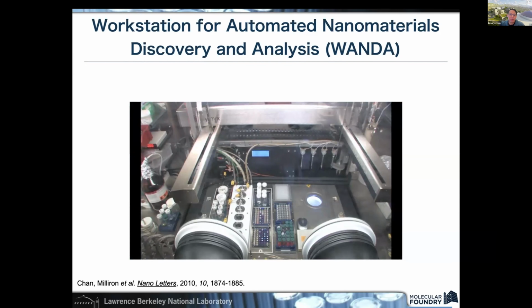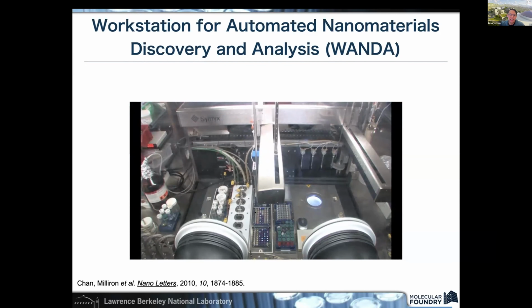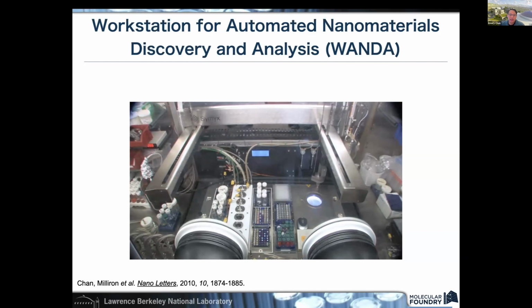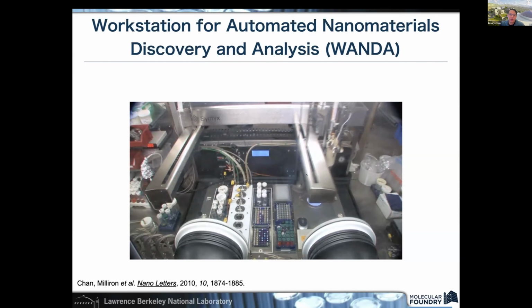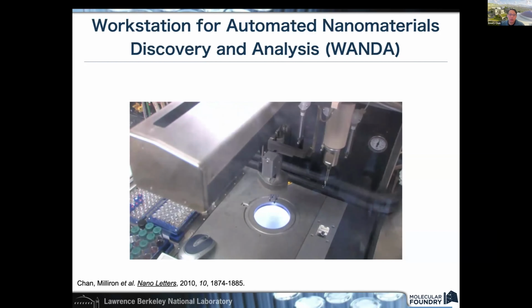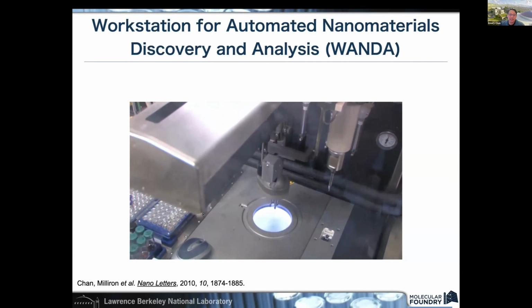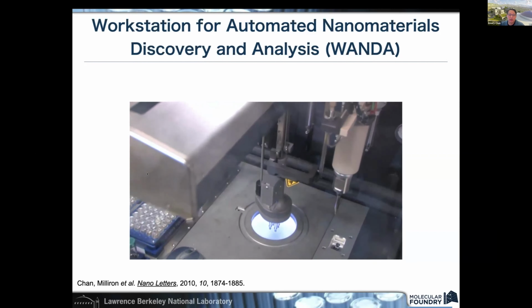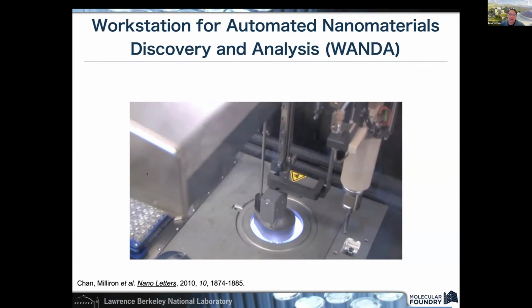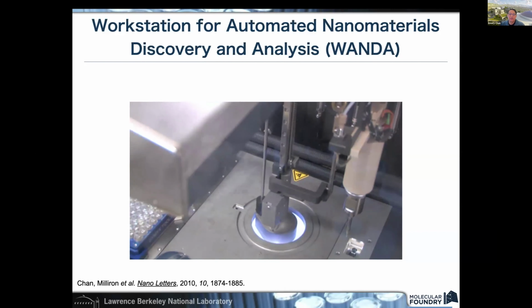So to step back a little bit, the reactions are performed in these wells of microplates or in this larger reactor. And so pipettes on the arms of these robots can slurp up reactions, precursors, inject them into a vial, heat and stir that vial, and then you have your nanoparticles.